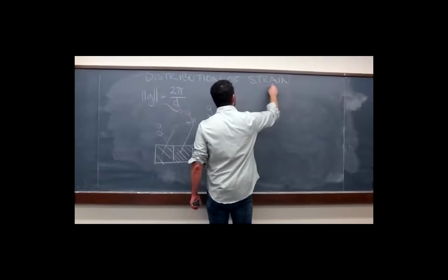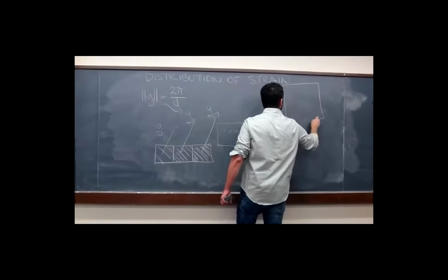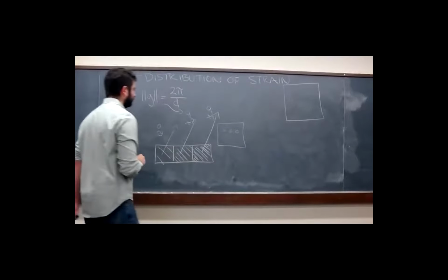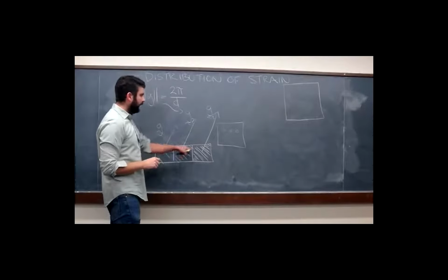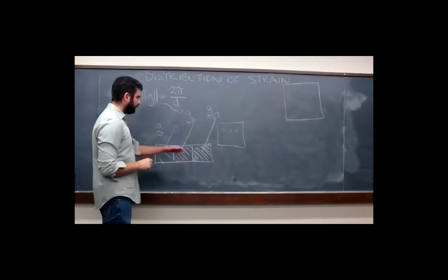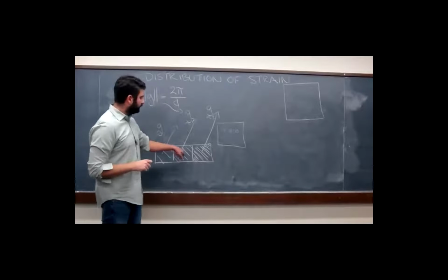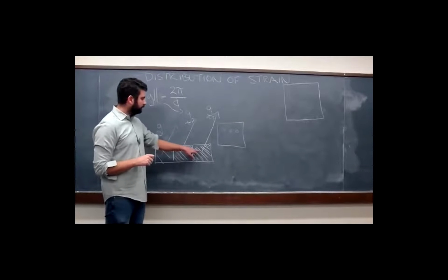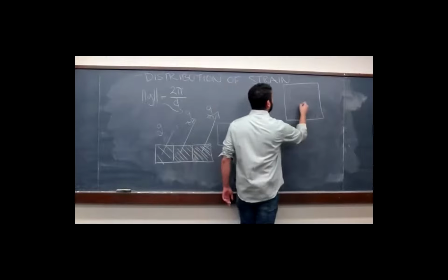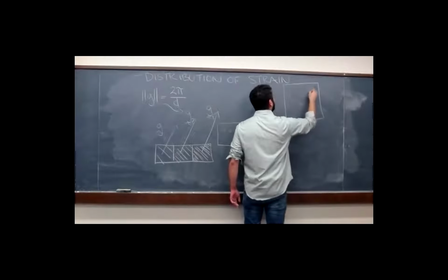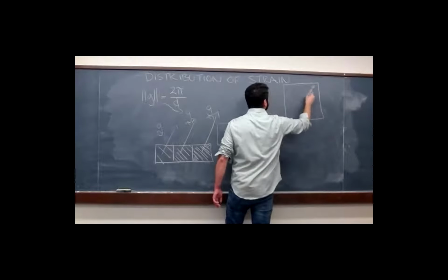Now, if we have the detector very far away, what we find is that the diffracted intensity becomes dominated by the angle at which it is emitted. And that means that since each of these has a different plane spacing, they're going to be emitting diffracted intensity at different 2 theta values. So they're going to show up at different radial positions on the detector.